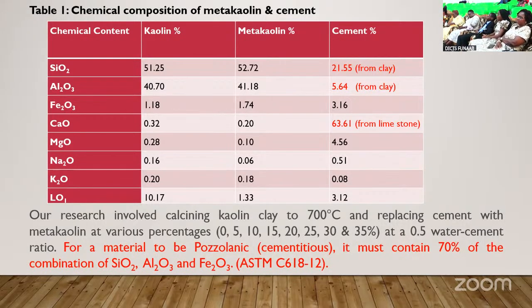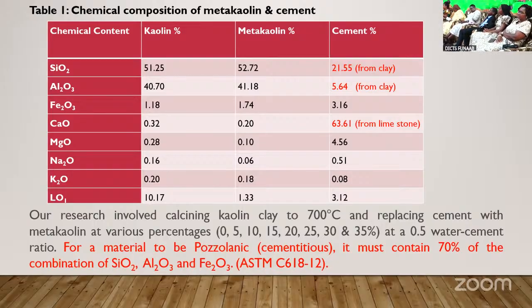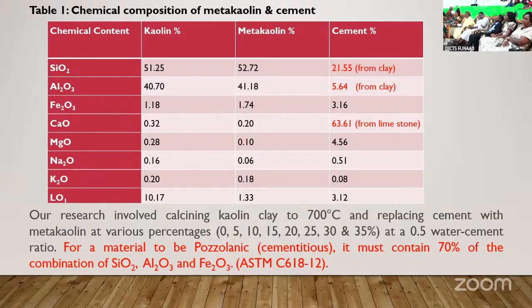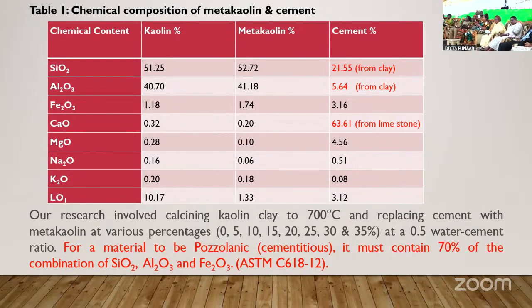For a material to be pozzolanic or cementitious, it must contain 70% of a combination of silicon oxide, aluminium oxide, and ferric oxide, according to ASTM C618. And from the table, we can see that our kaolin and metakaolin met this demand. And the cement, you can see the compounds in our cement also: 63.61% of calcium oxide, aluminium oxide 5.64%, and silicon oxide 21.55%.